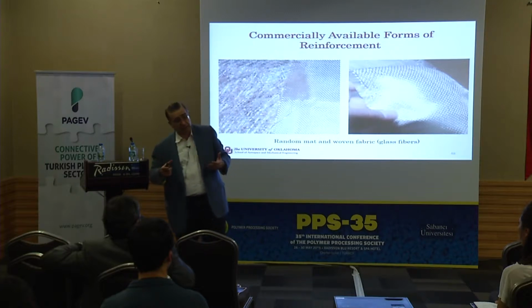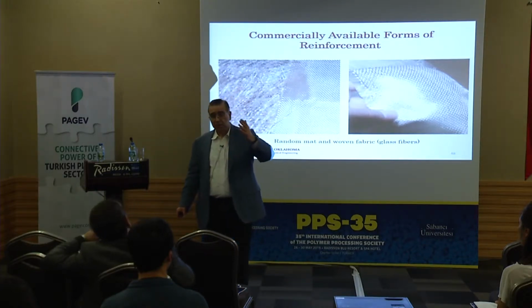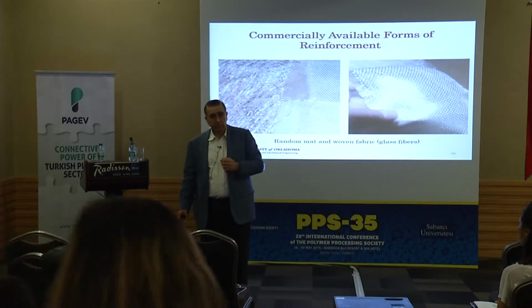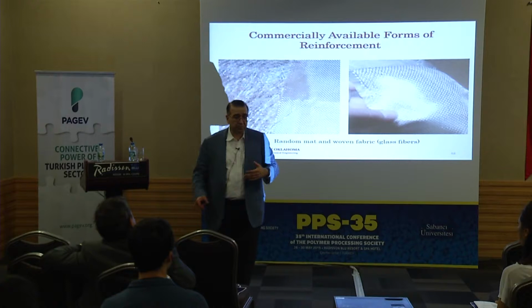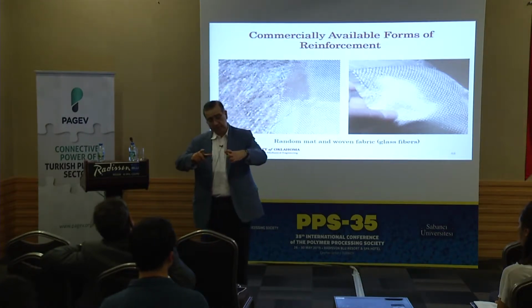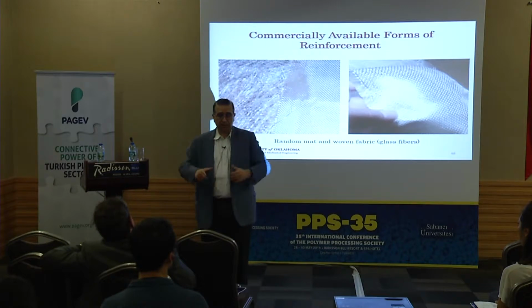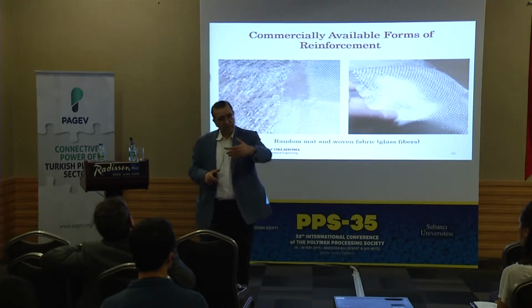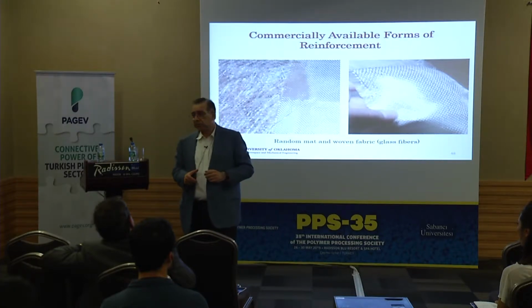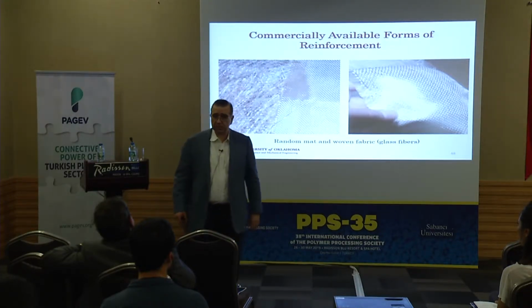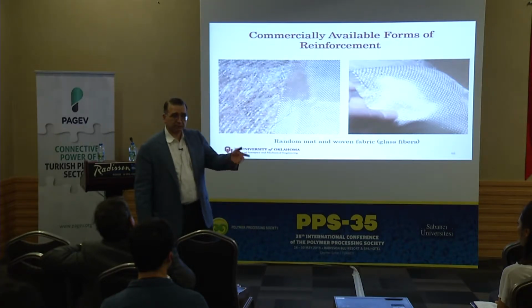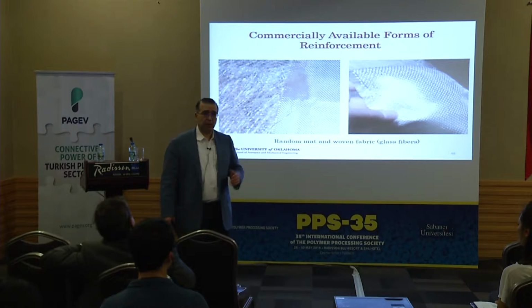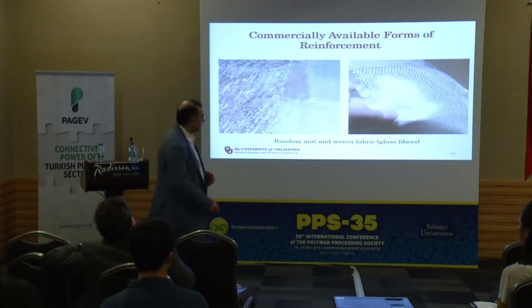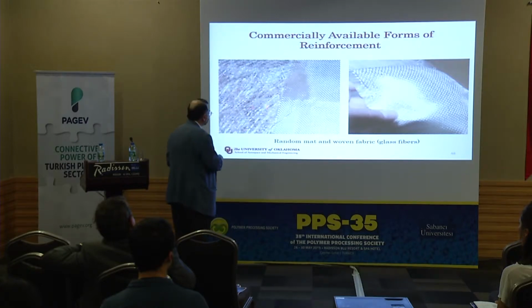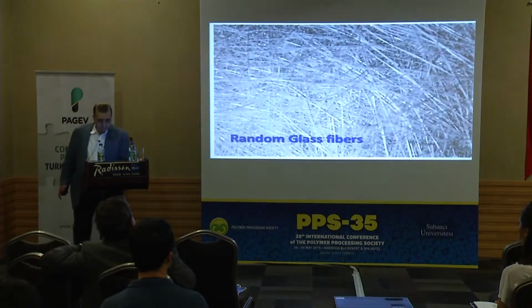So you might be designing the part to have 16 layers and the fiber content maybe 50 grams, and then you decide, okay, I'm going to cut this big and 16 layers. But then you might have 20% variation in the weight, which will give you quite a bit of variation in the fiber volume fraction, so your properties will be non-uniform from component to component. So you need to be a little bit careful, but there is nothing that is too bad when you are working with random mat fabrics.